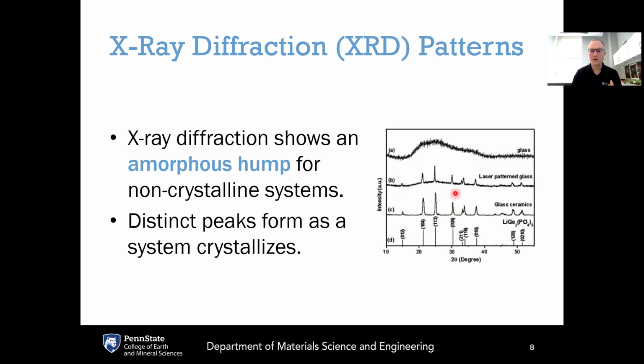And so if you use X-ray diffraction on a perfect single crystal, what you would see is a pattern as shown on the bottom here. Here you've got these perfectly sharp peaks. The peaks are perfectly sharp because it is a perfect crystal where all the unit cells are repeated perfectly in space, and the positions and the intensities would reflect the structure of that particular crystal.